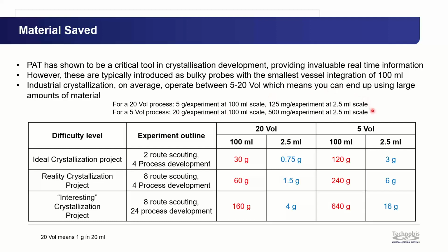But by being able to work at 2.5 milliliter scale with the Crystalline, you were able to reduce that significantly down to 125 mg for 20 volumes, or 500 mg for 5 volumes. And for one or two experiments, 5 grams might not be that much, but depending on how complex the crystallization is, this can start to add up. So typically crystallizations fall into 3 categories. First being ideal crystallizations. This can be where there's no other polymorphs lurking around. It's quite easy. You can cool down and get a good yield. So this could be 2 small experiments followed by a few fine tuning. That can be between 30 to 120 grams for just an ideal crystallization.